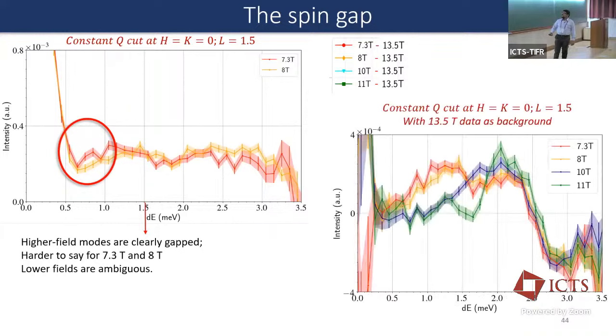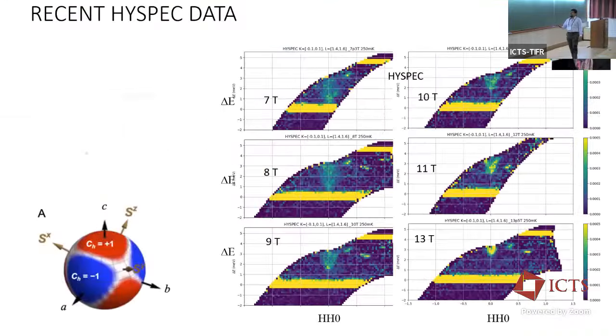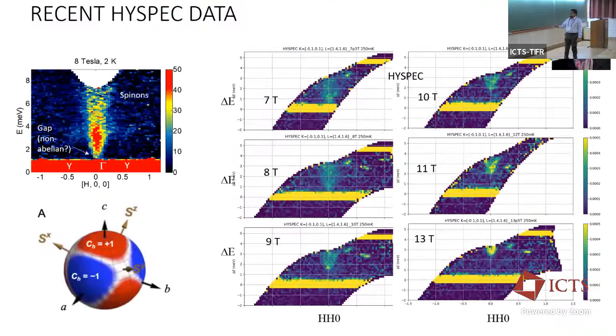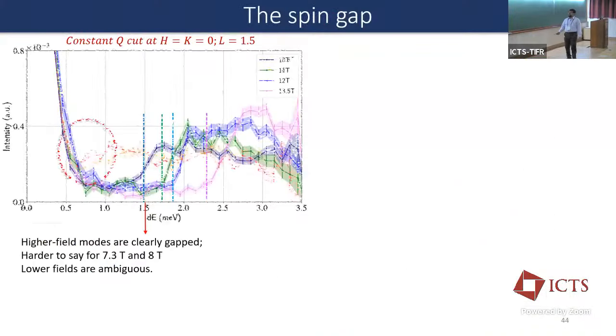So, not going into too much detail, what we went through is a pretty elaborate enterprise of trying to figure out how to subtract the background. What we were doing is taking 13.5 Tesla as our background. So let me show that to you once again. What we assume is that 13 Tesla or 13.5 Tesla is clean, which means that now we can take this data as the background to see whether these are gapped or gapless, or whether the modes are closing there. So that's basically what we are going through here.